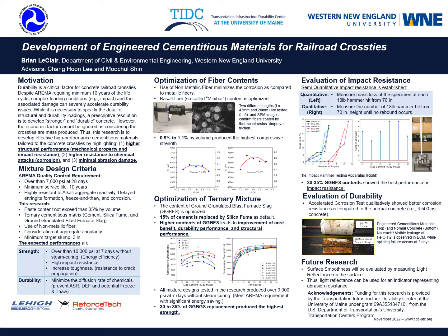AREMA has many quality control requirements that must be met. They require 7,000 psi strength at 28 days and a 10-year service life. They also require resistance to alkali aggregate reactivity, delayed ettringite formation, freeze and thaw, and corrosion. For our research, we expect to see 10,000 psi strength at only 7 days. We do this with a ternary cementitious matrix of cement, silica fume, and ground granulated blast furnace slag, as well as the use of non-metallic fiber. With this, we also expect to see a minimization of chemical diffusion that prevents alkali-silica reaction, delayed ettringite formation, and the potential freeze and thaw.